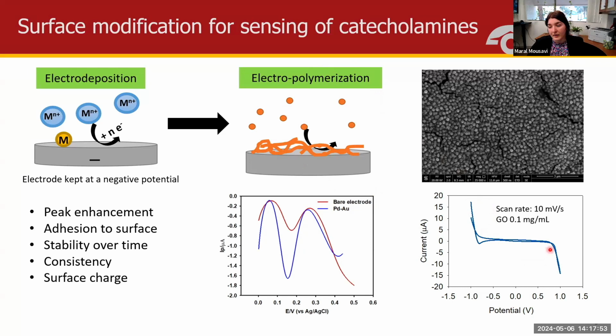And you're looking at the data that's collected during the polymerization. This mixture that is polymerized at the surface also contains graphene oxide nanoparticles. So a combination of the metal nanoparticles, electropolymerized polymer, along with the graphene oxide creates a high surface area, a porous structure that then enhances the signal for measuring catecholamines.